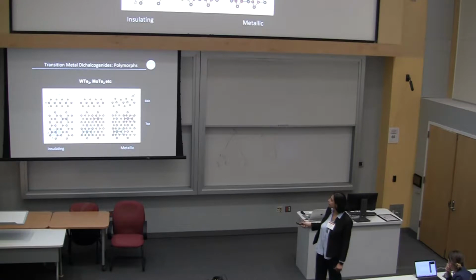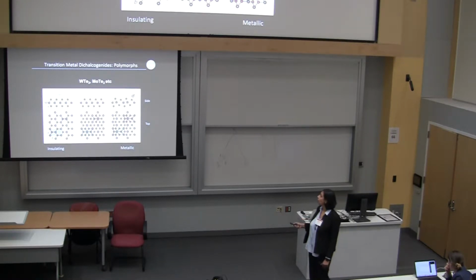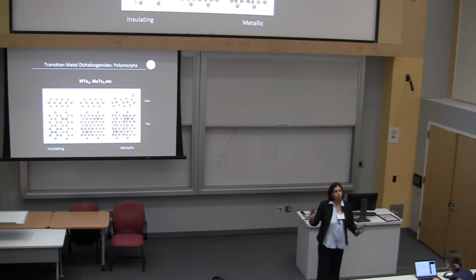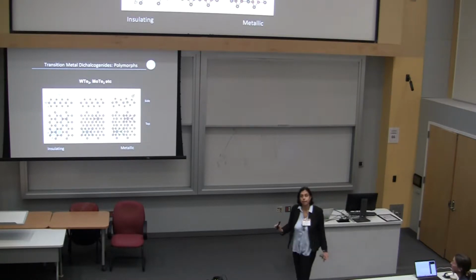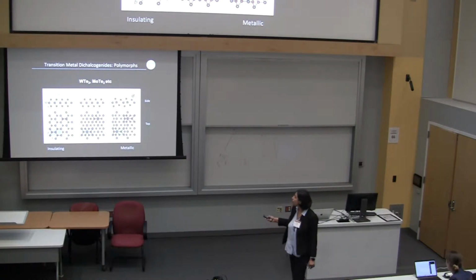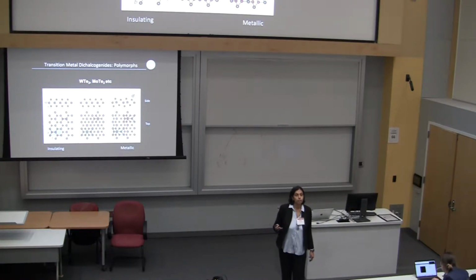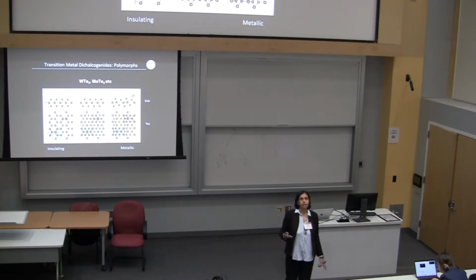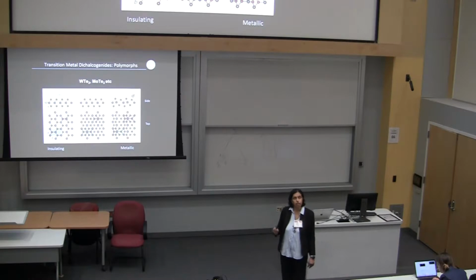The interesting thing is each polymorph actually has a different property. Often the 2H versions are insulating and the 1T prime versions are metallic, although this is not always true. For example, niobium diselenide, which is often found in the 2H polymorph, is a metal. It has multiple bands crossing the Fermi energy, so the chalcogen also matters.